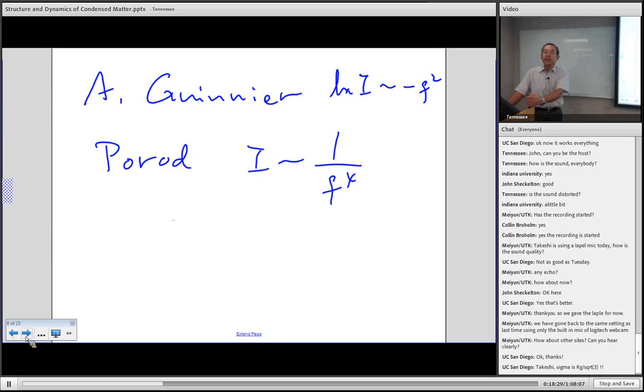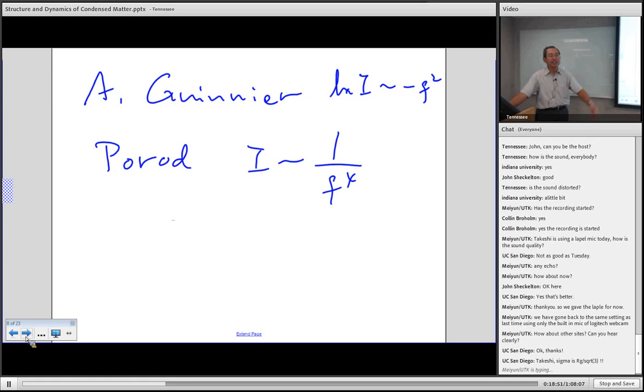So again, if the object is kind of Gaussian, and so the perimeter or edge is not clear, if the edge is fuzzy, if the shape is fuzzy, it's not like a Gaussian, right? In this case, you get like a Guinier law. But if the interface is quite well defined, if it is like a solid object where that edge is clear, then you get Porod's law. And in between you get